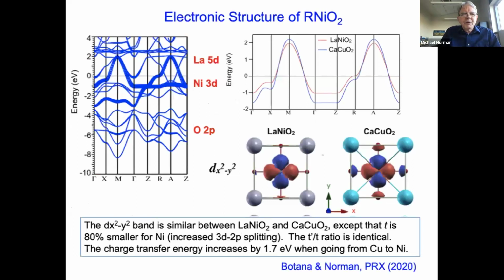So just a reminder, you do get a cuprate-like nickel 3D x squared minus y squared band near the chemical potential. If you look at the t hopping integral, it's about 80% of what you see in calcium copper O2. The t prime over t ratio, where t prime is the next nearest neighbor hopping, is identical to cuprates, but the charge transfer energy goes up by almost 2 volts when you go, say, from calcium copper O2 to lanthanum nickel O2.